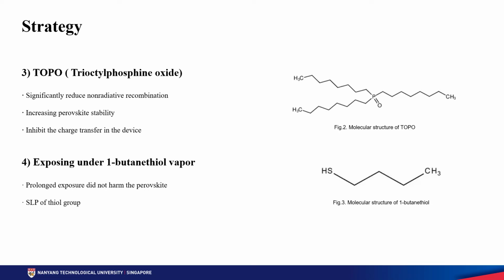And the authors also used another method, which is exposing the rough top surface of the perovskite to 1-butanethiol vapor, and found that prolonged exposure did not harm the perovskite. This is based on the self-limiting passivation, also called SLP, of the thiol group. No attaching sites for additional layer growth remain after the initial passivation, which ensures the damage of the perovskite will not happen, and the detailed mechanism of SLP of the group will be talked about later in the mechanism part.